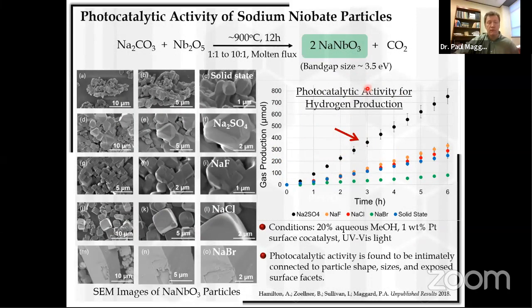And so here's one recent example that we reported, sodium niobate, which has a band gap size of around 3.5 eV. And you can see in the SEM images on the left, we have made sodium niobate by a solid state approach, which has very irregular morphologies, very large sizes. And then we've made it using a sodium sulfate flux, where we've mixed in a sodium sulfate in a 1-to-1 or a 10-to-1 ratio, together with the reactant sodium carbonate and niobium oxides.